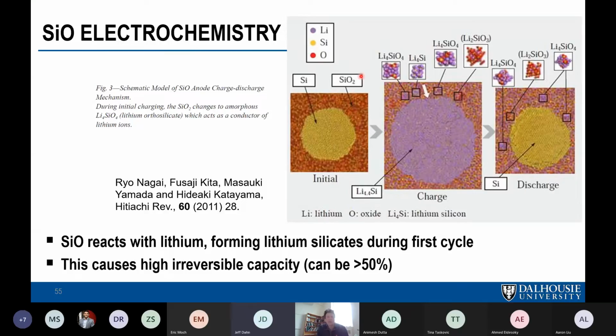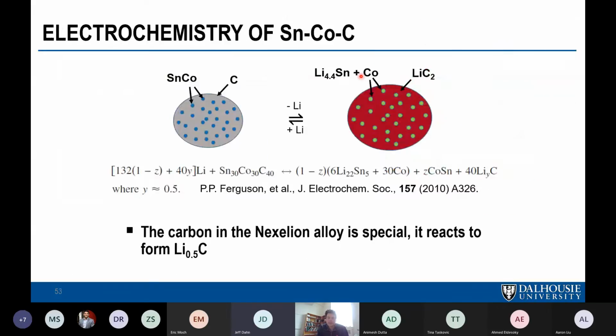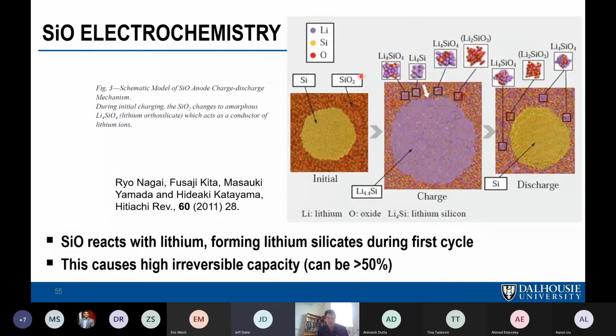And calculating volume expansion for SiO is interesting because you cannot use those formulas that I had before. I should have written a succinct formula here, but basically the lithiation reaction is lithium plus SiO gives you Li4SiO4 plus lithium 15 silicon 4. And you have to use those reaction products to calculate what the volume expansion is, because what you're forming is not an alloy. This is now a compound, a new compound. And so you can't use those equations that we had for pure alloys before.